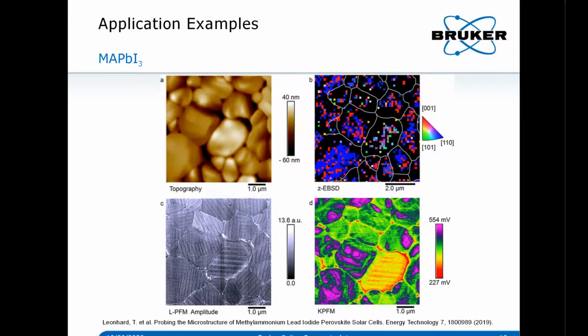Another example shows how to combine different kinds of nanoelectrical and nanomechanical modes together with PFM to give you the full spectrum material characterization on the AFM platform. This is a perovskite material here, and clearly from the topography we see the different grains separate nicely. And from the PFM, here we are looking at the in-plane PFM response. You can see even within different grains, you have many domains distributed over the whole grains, which tells you that the domain distribution within a single grain is not homogeneous.